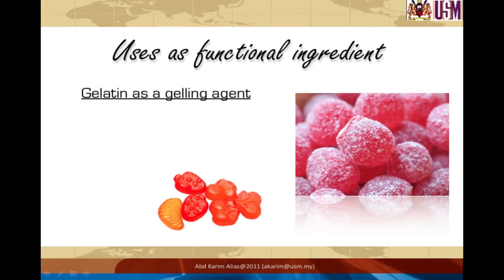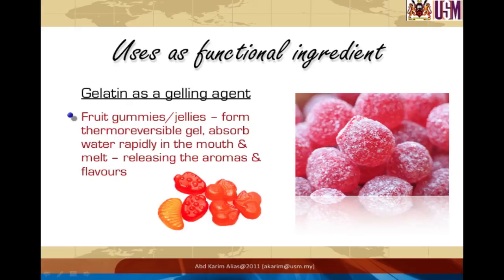Now let's look at specific food applications of gelatin. In fruit gummies, gelatin is used as both a gelling agent and a texturizing agent. In the mouth, the gummies absorb water rapidly, the melting point decreases to body temperature, the gel melts, and aroma and flavors are released. Other gelling agents such as agar or carrageenan cannot demonstrate the same properties. The choice of gelatin type — Type A or Type B — is important because it affects the texture of the gummies. In most cases, the use of high bloom Type A gelatin is recommended.